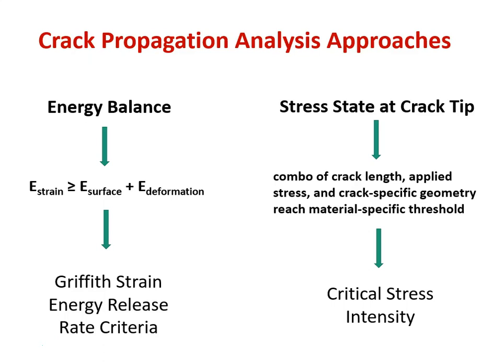In the case of the energy balance, we'll go over concepts like the Griffith strain energy release rate criteria. These two are obviously related, and for certain simplified cases, they equate to one another. But looking ahead, it's really the stress state at the crack tip approach that has become most prevalent, and for which you will find the most data, and that's probably how most of your designs will go, and that's what we'll cover the most in the class. But we're going to use the energy balance as a way to simply understand the concepts that go into crack propagation, because it's a lot easier to understand conceptually. Both approaches are correct, both approaches are valid, but most of the bulk of test data and computational modeling analysis have gone into the stress state of the crack tip approach.